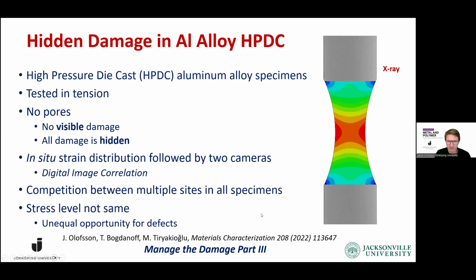So you can see the strain field in the picture here. That's what we would expect to see in a tensile sample when we apply a tensile load. So what we did is that we used digital image correlation. We put 2 cameras to observe a pattern that we paint on these samples, so we can observe in situ the strain distribution and how it proceeds when we increase the load. And as I said, the stress level is not the same throughout this. So we have an uneven loading of the material, which also creates an unequal opportunity for defects. So as we will see in the slides, there will be a competition between multiple sites.